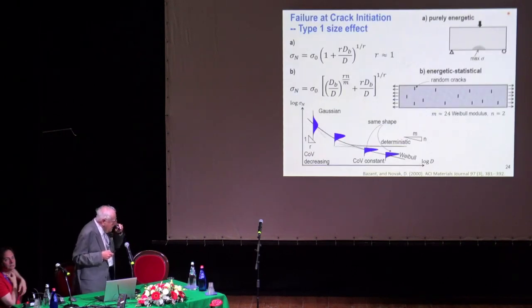Now there is a different size effect which occurs when the geometry is positive from the beginning, which means the energy release factor increases with crack length at constant load. And then you obtain failure right away, as soon as the fracture process zone forms. If the zone of maximum stress is small, like on top right, then you get a deterministic size effect, which ends up from a slope going to a horizontal asymptote.